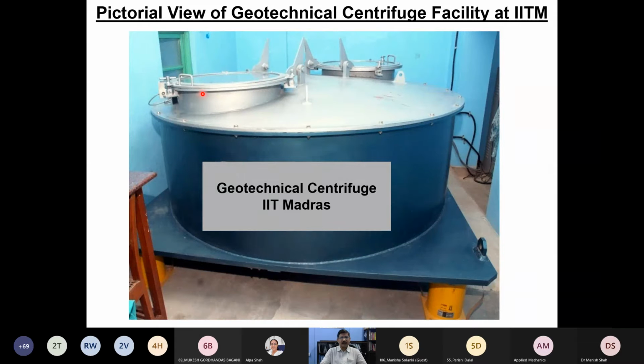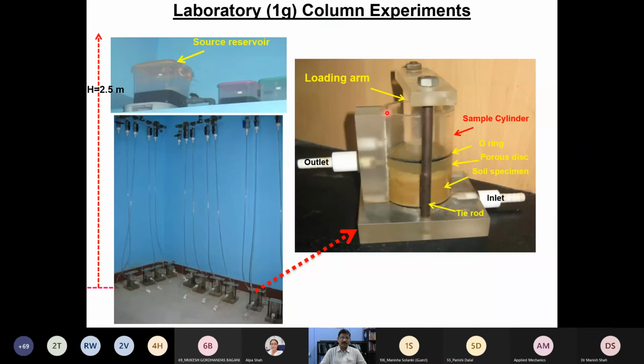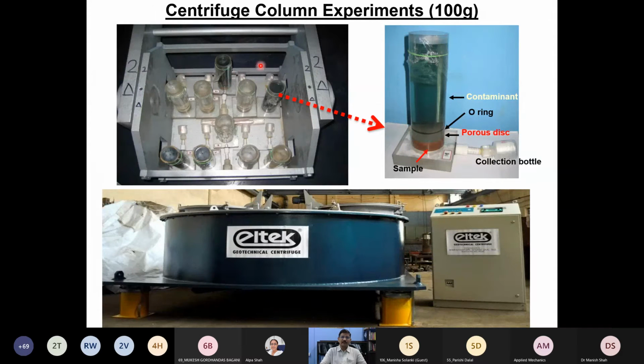The centrifuge may look like this, and this is a viewing window. There is another viewing window, and internally, if you look at it, your bucket will look like this. The bucket has a size of something like 0.5 meter by 0.5 meter, where we have placed around 10 column flow-through experiments. This is the liner material, where the contaminant is allowed to stagnate above, and once it is subjected to the accelerated environment, the effluent is collected. Once you get the effluent, we normalize the effluent concentration versus the influent concentration, Ct by C naught, versus time.